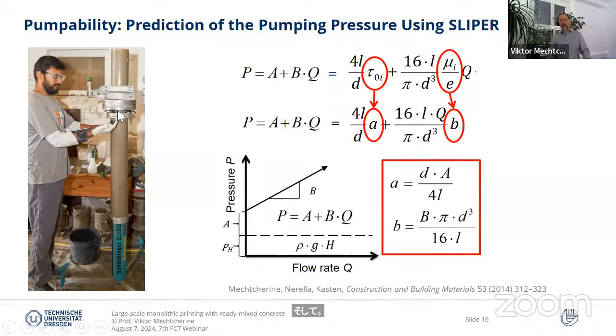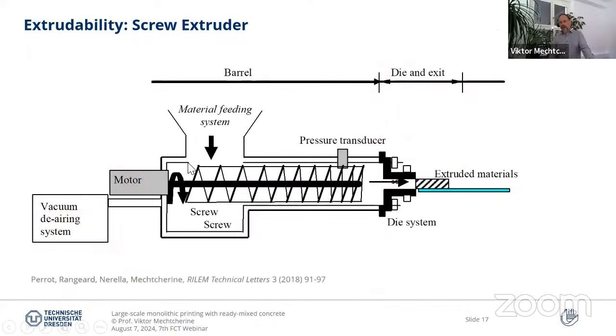And this kind of a device can be used in the practice of construction very easily on the construction site. It's pretty robust and works very nicely. So it's a little bit more difficult if you go for characterization of extrudability, because the geometrical boundaries are much more complicated. Usually we apply a screw system here, and we can predict the flow rate of the material pretty well, depending on the speed of rotation of the screw.